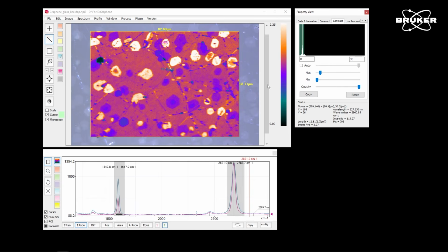So multi-layer, bilayer, monolayer. With that, we can say our sample mostly consists out of monolayer. It has some bilayer islands where the CVD growing process worked sufficiently. And then we have a few chunky multi-layer bits that is shown here and here by the dark green black color.